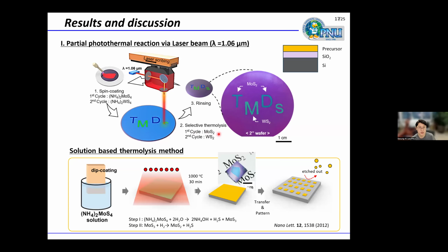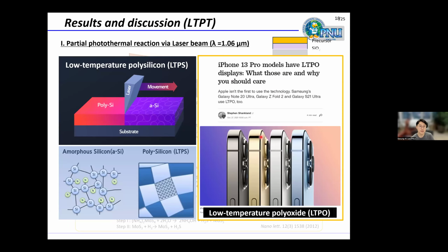With this condition, we can directly pattern the 2D materials such as MoS2 and WS2 without residue in a simple and fast process. The procedure involves just 3 steps. First is spin coating the precursor, then laser scribing, and then solvent washing to remove the unexposed region. By repeating this step, we can fabricate additional 2D materials and build a more complex structure. This approach for synthesizing MoS2 is quite similar to the LTPS and LTPO process, so we denote this method as LTPT. Here, the T represents the transition metal dichalcogenide.